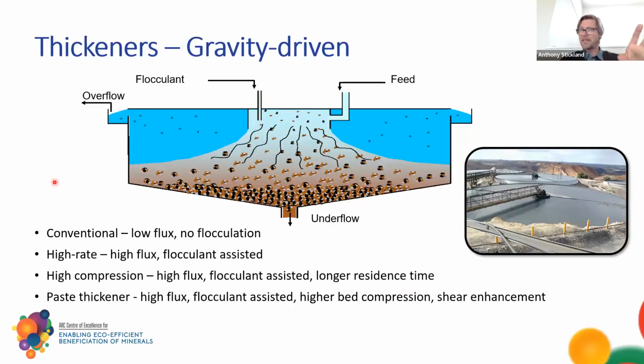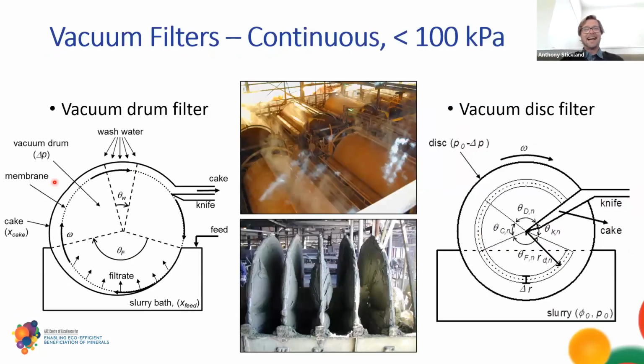I could talk for the entire hour about thickening if you wanted to, but I'll keep moving. Different types of filters that you see. There's things like vacuum drum filters, which is a large cylinder with a filter cloth around it. The inside of the drum is under vacuum, and as it passes through the slurry bath, it builds up a cake, then comes out of the slurry bath.